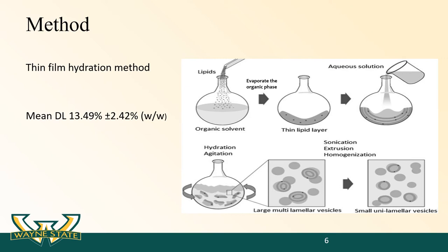On the second day, liposomes were extruded through a 150 nm polycarbonate membrane to create small unilamellar nanoparticles, followed by purification using a 200 kilodalton molecular weight cutoff centrifuge tube to separate the free CD40A from the core-encapsulated CD40A.